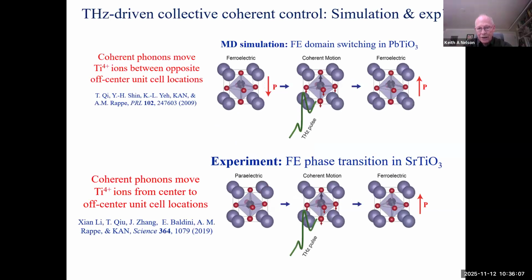So it's strontium titanate, and it's paraelectric. This has what's called a quantum paraelectric phase. It actually never goes ferroelectric, unlike many other members of this family, like lead titanate and many others. Strontium titanate actually doesn't have a ferroelectric phase. It approaches it. It looks like it's going to turn ferroelectric, but it never does. And that's because the potential minima away from the center for that ion are so shallow that even the zero-point vibrational energy is higher than those very shallow minima.